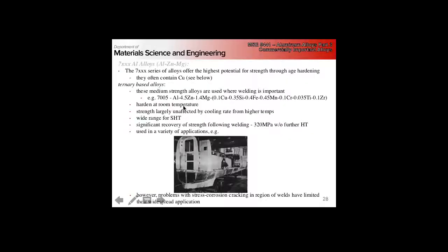The ternaries harden at room temperature, and again, now I'm going to say something confusing. Remember we talked about vacancies and GP zone formation. I talked about how cooling rate was really critical because if you cooled too slowly, you had a chance to anneal out your vacancies and make it that much harder for GP zones to form. Here, these ones tend to be largely unaffected by cooling rate, which implies that our hardening properties are less critical on GP zone formation. So it's easier to nucleate and grow a more homogeneous distribution of the other intermediate phases.